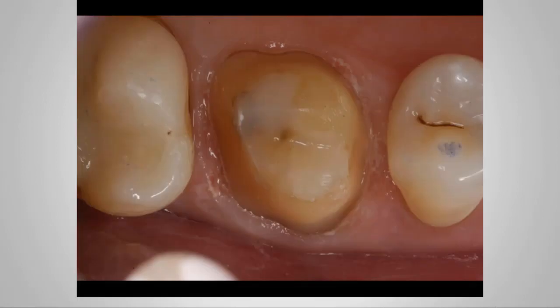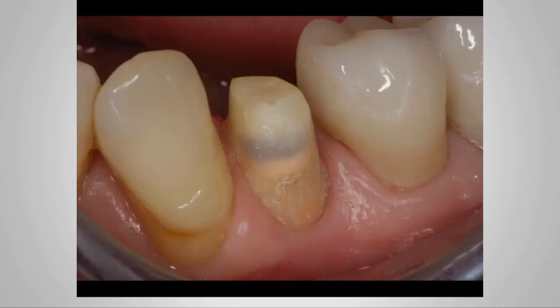So this is the typical prep that we would consider a conventional crown prep, and this is appropriate for zirconia. Zirconia, you can really prep a lot of different ways. I think that, like any other restoration, having a little more reduction is not going to hurt you. If you're trying to be conservative, you also have the option to be strong and still be very conservative. Most of the crown preps that we see, taking old crowns off, you're going to have a preparation very similar to what you're seeing here, which is fine for zirconia.